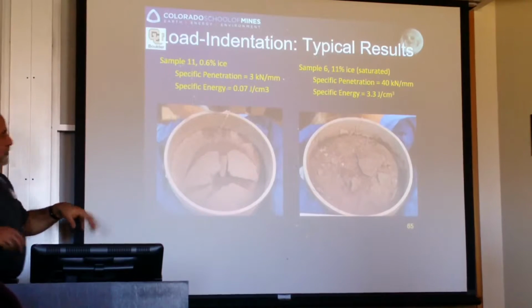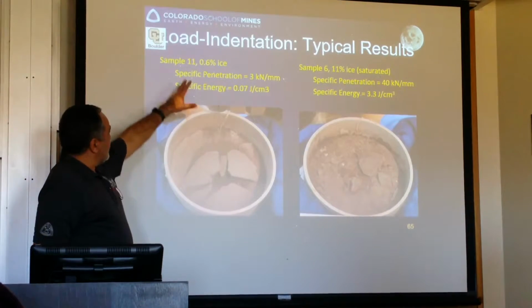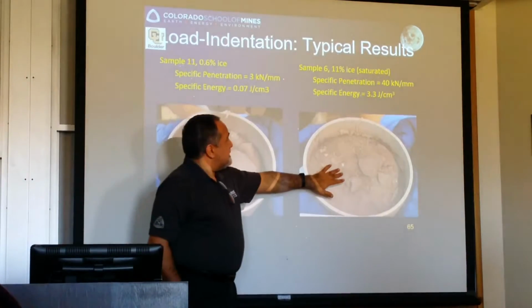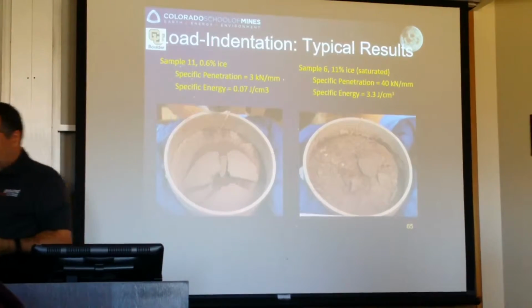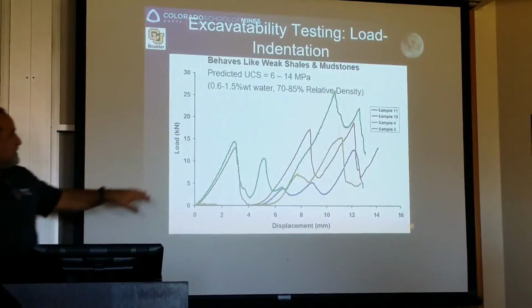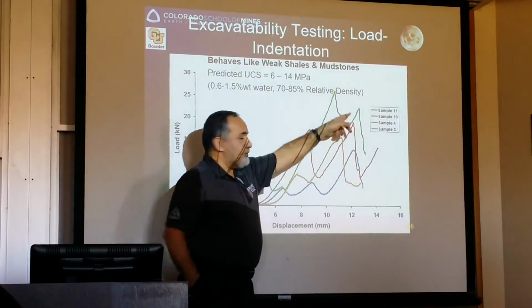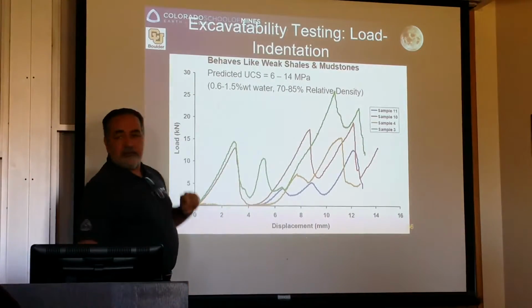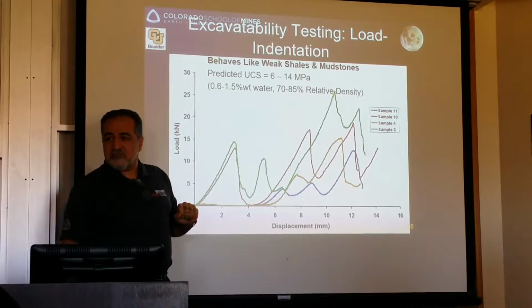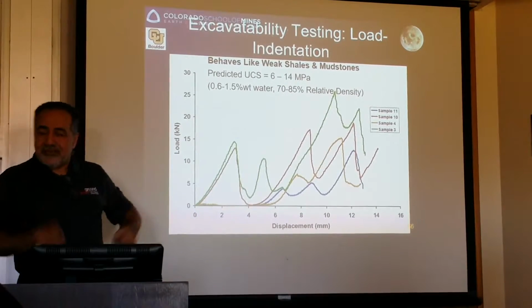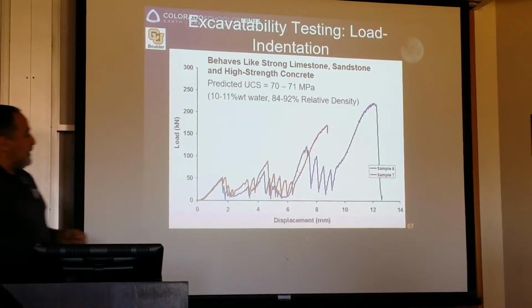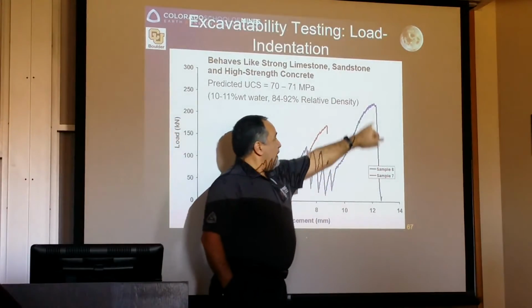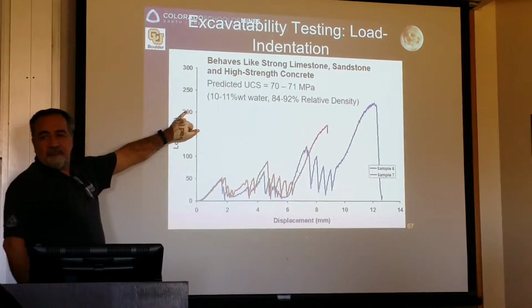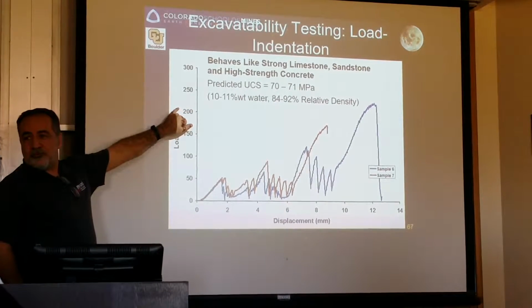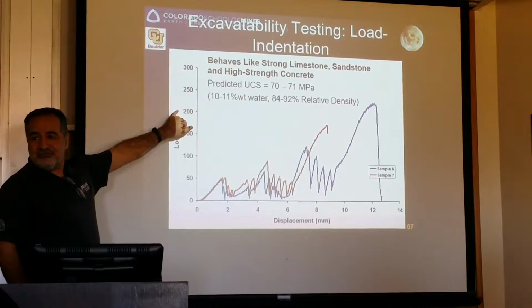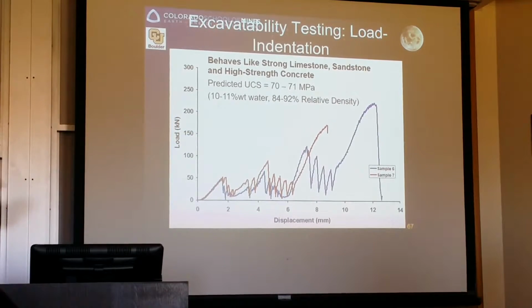We did additional testing for penetration. This is actually 0.5% or actually 0.6% water. This is 11% water. Penetrating into that material was difficult. This is 0.5% water. If you go to about 12 millimeter penetration, we need a 25 kilonewton, 2.5 tons. It's not a joke, but it's still, okay, you can think about it. But for 11% water content, look at the force. 200 kilonewton, 20 tons. Boy, that's a bummer, right?